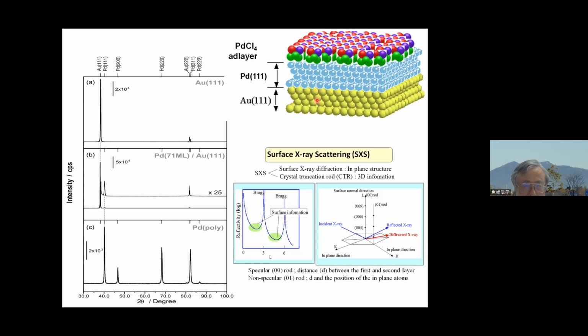So we carried out surface X-ray scattering using synchrotron radiation. Surface X-ray scattering can be divided into two. One is surface X-ray diffraction, where the X-ray is coming in and diffracted by the surface structure, and the other is crystal truncation rods like this, so that we can get 3D information. In bulk X-ray diffraction, we see only this black peak, but in the case of surface X-ray scattering, the information of the surface can be obtained from these regions.